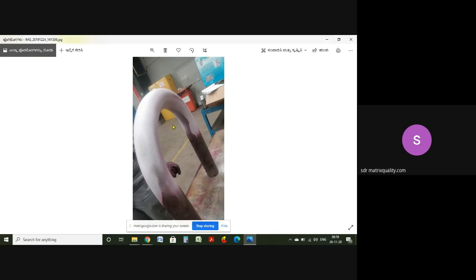Once the developer is applied, if there are any cracks or holes or defects, the penetrant has gone inside and stays there. When you put the developer, the developer absorbs or pulls out the red color penetrant. So on the white background, we can see red color dots if there are any defects. This test is done to qualify that there are no defects. And in the visual test, normally we can see wrinkles and any bulging, or dent marks of the die, if the die is not properly ground. So all that is done.